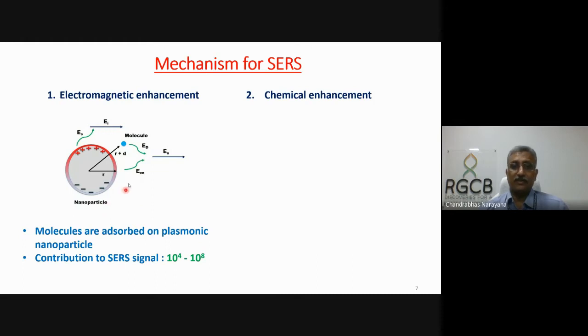The electromagnetic enhancement is basically what I said. You create a dipole, and that oscillating dipole produces electromagnetic radiation. So the molecule sees not only the electromagnetic radiation of the incident light, but also the electromagnetic radiation of the dipole oscillating here. And again, there will be a cascading effect, because you would actually have Rayleigh scattering from the molecule, and that Rayleigh scattering again causes dipole movement, and then it is like a multiple cascading effect. And all of a sudden you see that the electric field which is incident on the molecule is going to be very, very large. And that's why you can get an enhancement of 10 to the power of 4 to 10 to the power of 8 in the case of electromagnetic enhancement.